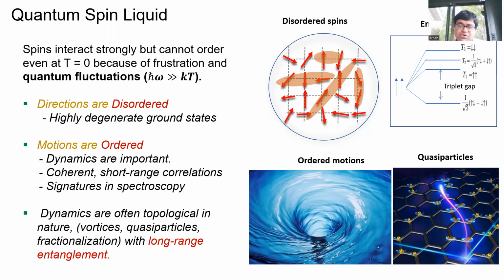However, when you drop a stone in the water, you form ripples. These ripples are very, very ordered. They have a very nice order to them. They kind of go out in spherical shapes. And as we see in a liquid, although the individual microscopic motions are all disordered, there is overall macroscopic orderliness in the system, especially in their motion. Those are the emergent motions that we get in the quantum spin liquid. So what we find is that in a quantum spin liquid, somehow the directions are all disordered, but the motions are all ordered, which also means that it's the dynamics which are the most important thing.